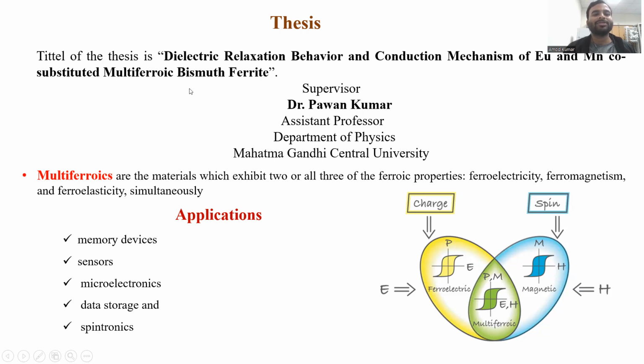There are some points on bismuth ferrite. Why am I interested in bismuth ferrite? It is an inorganic chemical compound with a perovskite structure. It belongs to rhombohedral crystal symmetry with space group R3c. And we are interested in Eu and Mn. Eu is doped at the Bi site and Mn is doped at the Fe site.